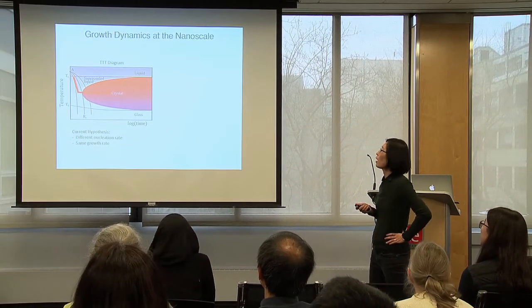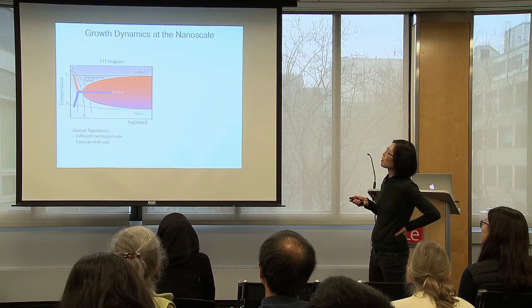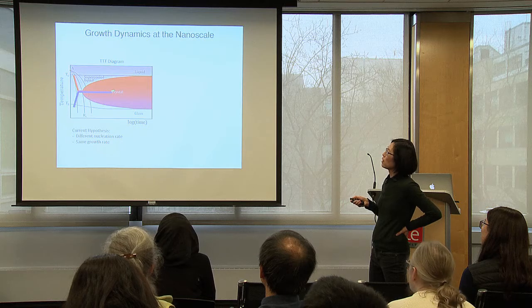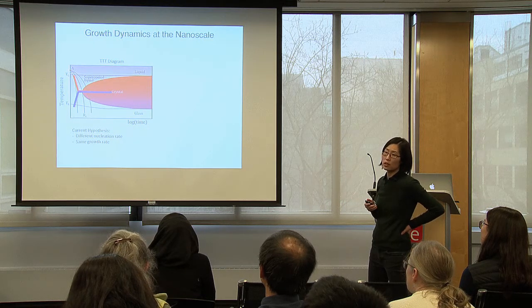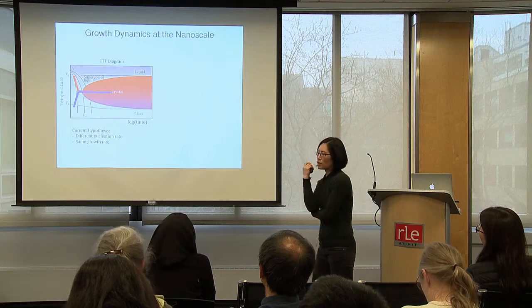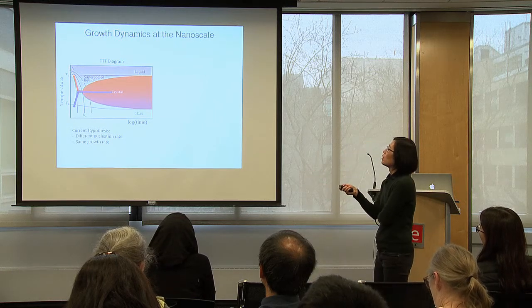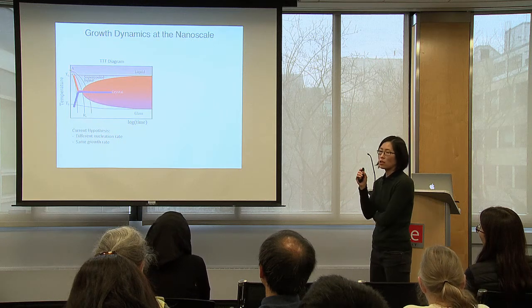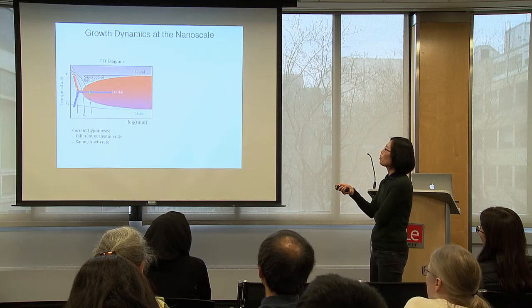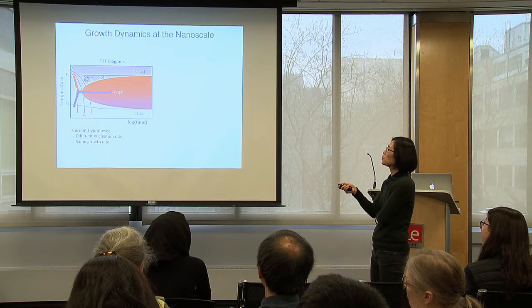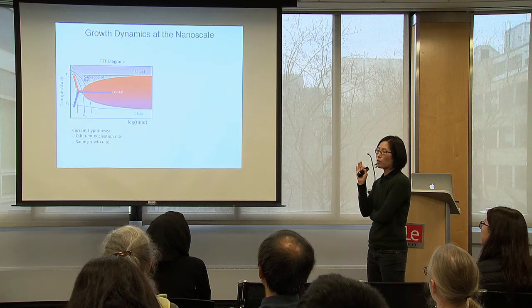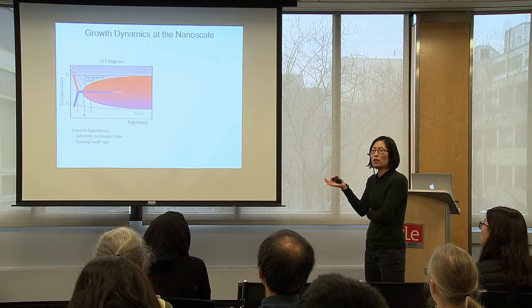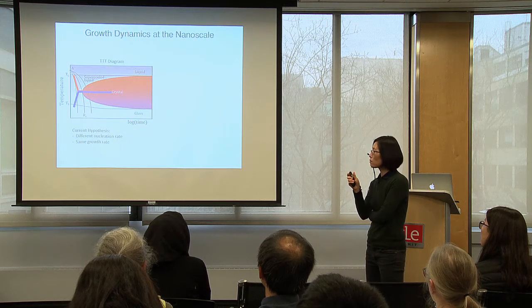So now we looked at doing isothermal experiments, where we directly go to a set temperature and watch the grain growth. Okay? So you can imagine doing it in two different ways: coming down from the liquid side and doing crystallization, or heating from the glass side and doing crystallization. So the simple, naive classical nucleation theory will tell you that because you're coming from two different sides, maybe the nucleation rates would be different. But if you are at the isothermal temperature for quite some time, the growth rate should be the same, because growth rate is diffusion, and diffusivity is purely a function of temperature.